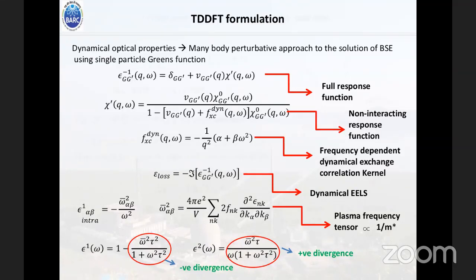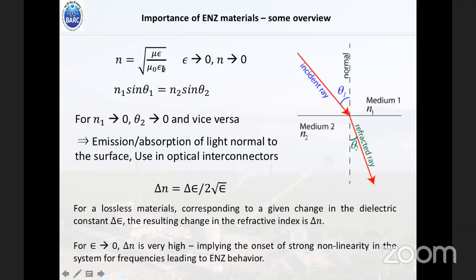These are also potential ENZ materials, that is epsilon-near-zero materials. If epsilon tends to zero, then from this simple relation n should also tend to zero, and from Snell's law, if n1 tends to zero, then theta 2 tends to zero, and vice versa. So emission and absorption of light should be normal to the surface.